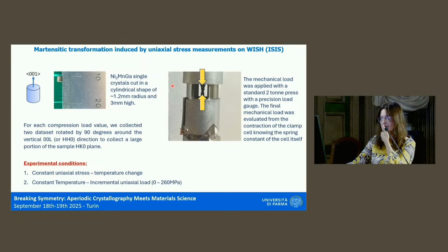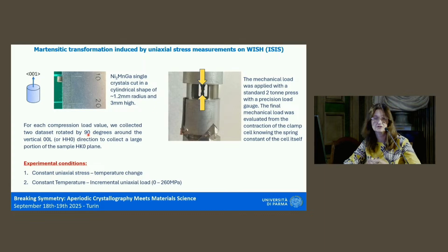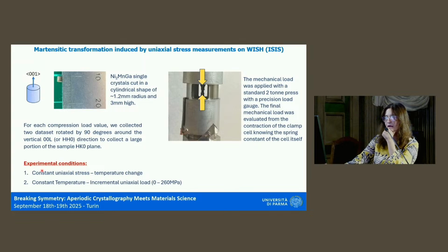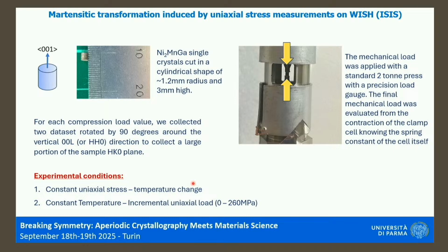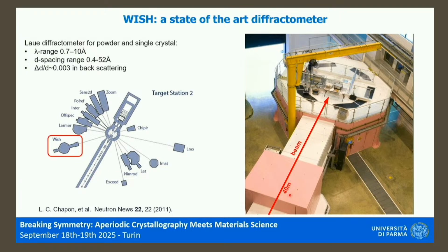Everything was really, how to say, analogical, because we put this clamp in the WISH diffractometer that is located at the Target 2 station at ISIS, a large facility, because we use time-of-flight neutron diffraction to collect single crystal patterns. And we rotated by hand this clamp with the crystal by 90 degrees in order to explore a larger portion of the reciprocal space. How do we work? We keep a constant uniaxial stress and change the temperature, or eventually keep the temperature constant and change the mechanical load. Okay, so you can see here a picture of the WISH beam line. The sample was located there.